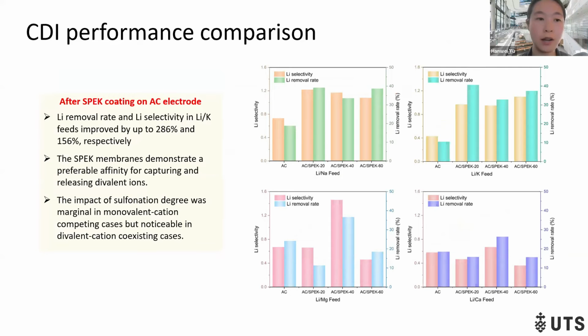After SPEK coating on the AC electrode, lithium removal rate and lithium selectivity in the lithium-potassium feed improved by over 200% and over 150% respectively. And the SPEK membrane demonstrates a preference for capturing and releasing divalent ions. The sulfonate degree has minimal impact in monovalent cases, but a noticeable effect in divalent cases.